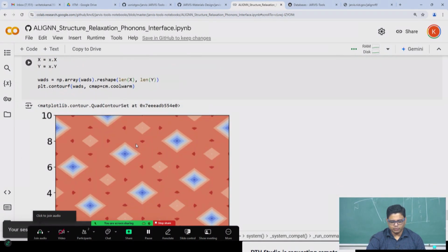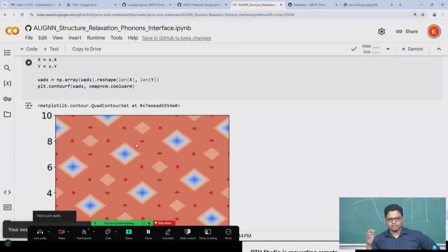My favorite part is this part, where it can be very useful when you want to calculate the low energy structure. Because in the past, people just did the Zur algorithm, put the small unit cells together, and said this is my structure. Nobody wants to do the XY scan, but it's quite important. And actually using this method, you can also calculate stacking fault. How many of you know stacking fault? Stacking fault is very important, especially when you have an alloy system or metal system like this. So you want to calculate where the unstable stacking fault and stable stacking fault are, and based on that your dislocations and other things are guided. So this can also be useful for this kind of application.